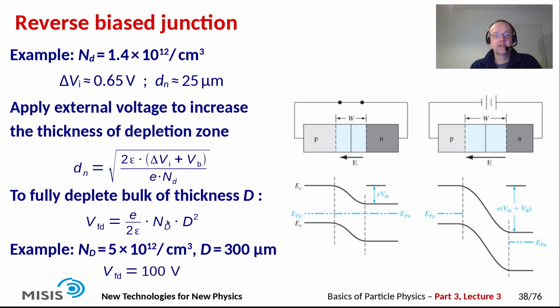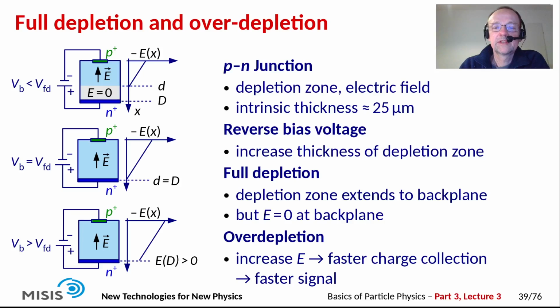Now again, putting in typical numbers for the thickness of the detector and doping concentration, we can calculate what the so-called full depletion voltage is, the voltage that is required to fully deplete a detector of thickness D. And what we find is that this is of the order of 100 volt if we put in these values here. So by creating a p-n junction between the implant and the detector bulk, we get a depletion zone and we get an electric field inside this depletion zone. But the intrinsic thickness of this depletion zone is small. So we apply an external bias voltage between the implant and the backplane of the detector in order to increase the thickness of the depletion zone.